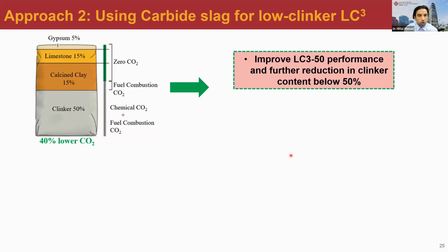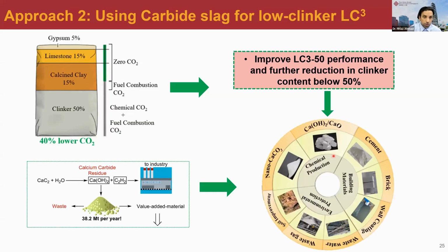Typically, when we talk about LC3, we are talking about LC3-50, which means that we are replacing up to 50% of the cement with limestone and calcined clay. So this cement has almost 40% lower carbon emissions. And so the goal of my research was to further reduce the amount of clinker in this system.